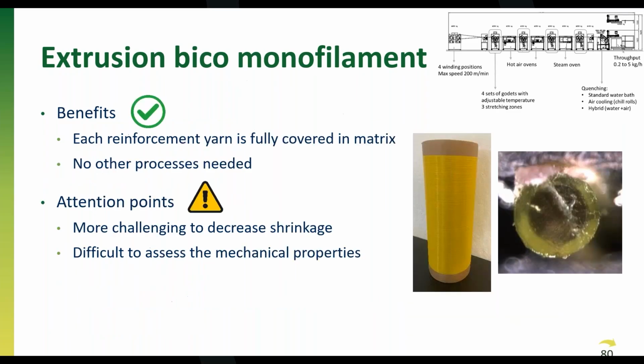Now there are some benefits, but also some attention points here. The benefit is that each reinforcement yarn is already fully covered with matrix, so you don't have any dry spots. You limit the amount of voids possible within the composite material, and no other processes are needed. So you don't need any commingling, etc. to produce the yarn. You produce the yarn and you have it readily for using in, for example, weaving to make fabrics or to produce UD tapes.